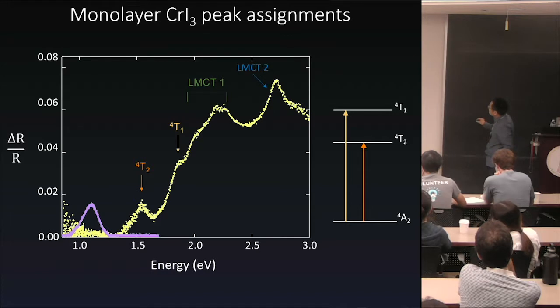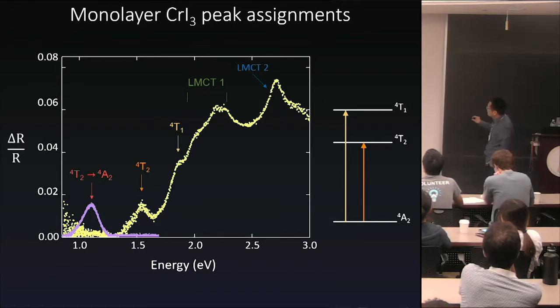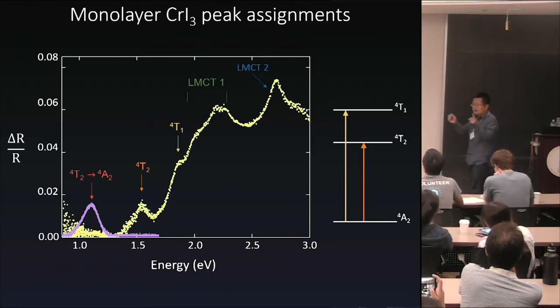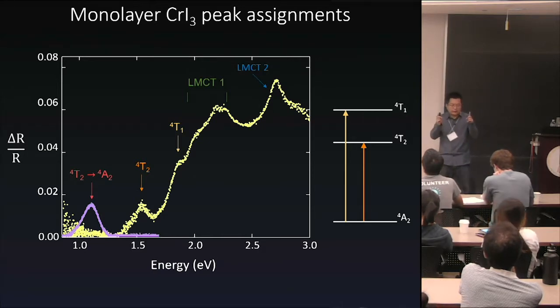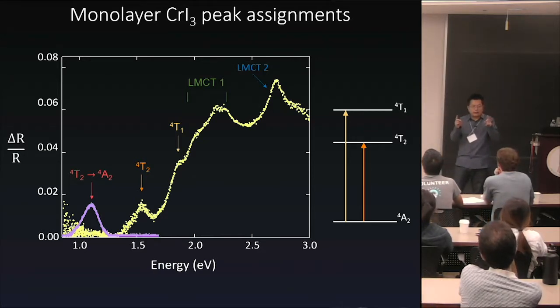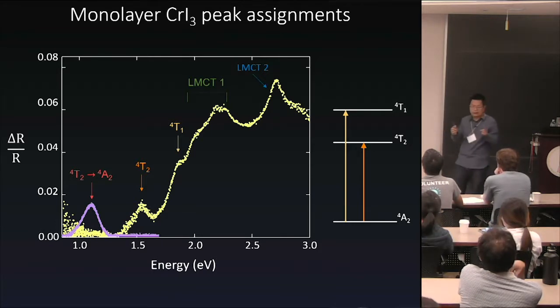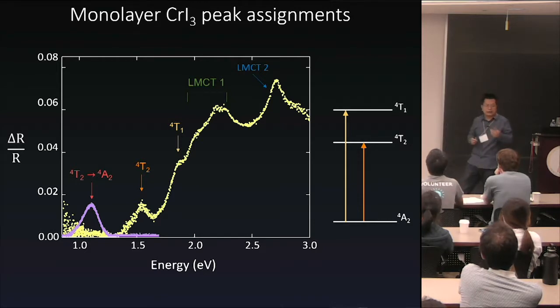Then the luminescence I show here is coming from 1.1 eV, right? It's also from the lowest ground state, but there's a huge energy difference between the absorption and this luminescence. This difference basically shows there's an extremely strong electron-phonon interaction. This shift is coming from that. Basically, it's a measure of the Huang-Rhys strength, the electron-phonon interaction.